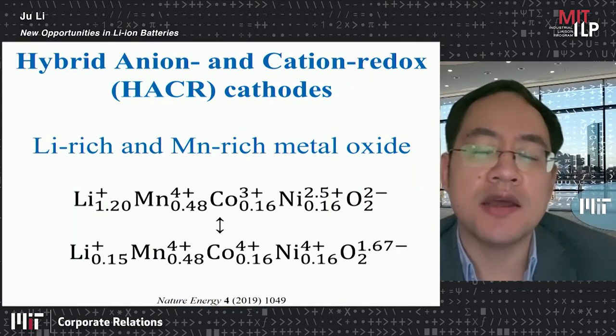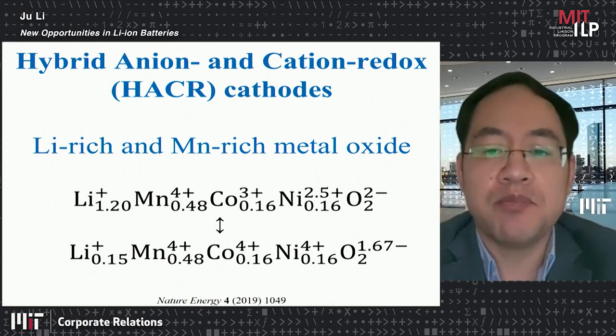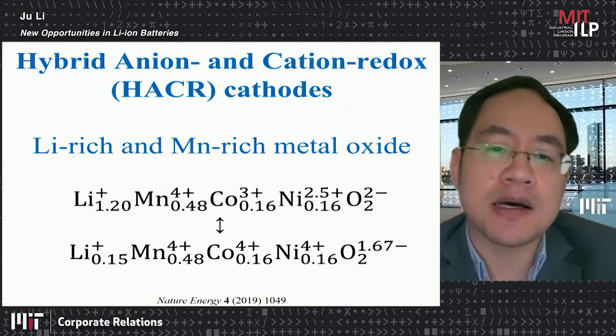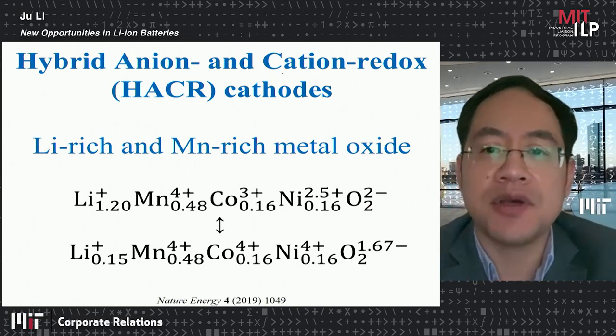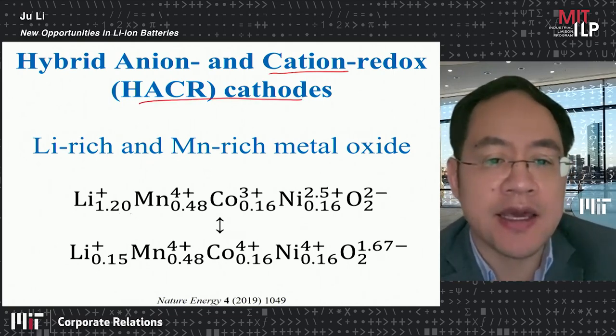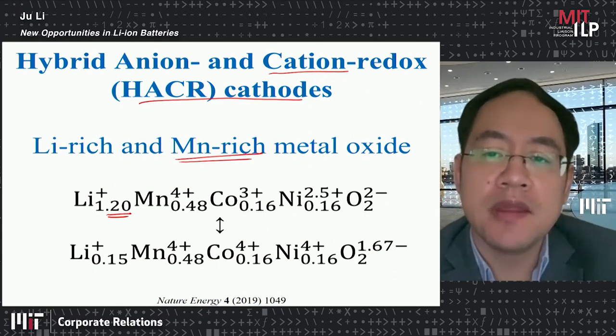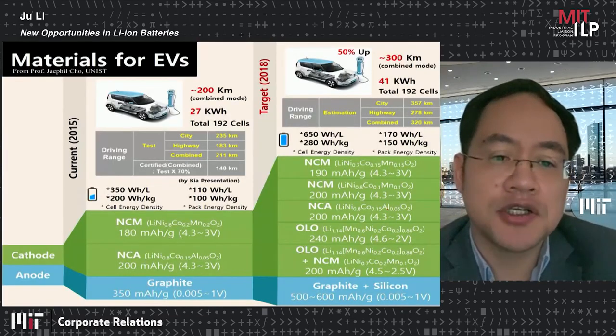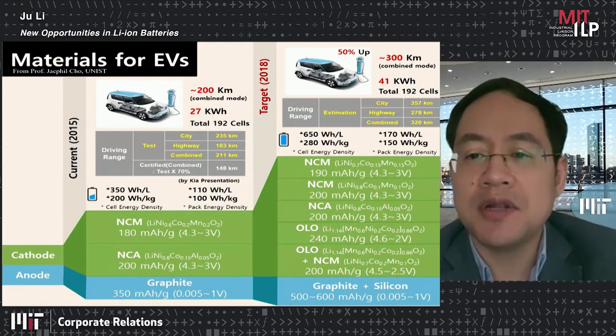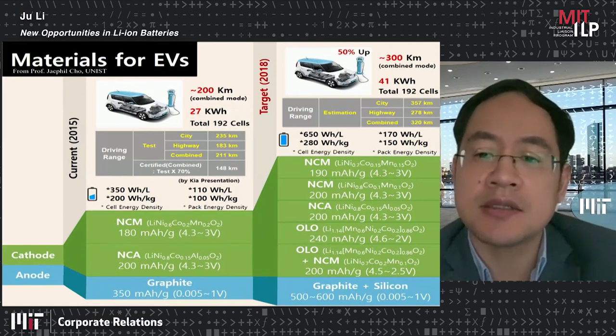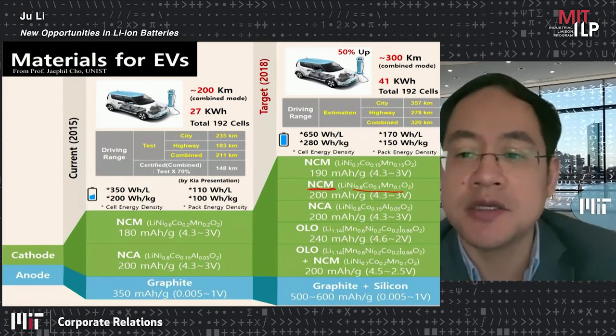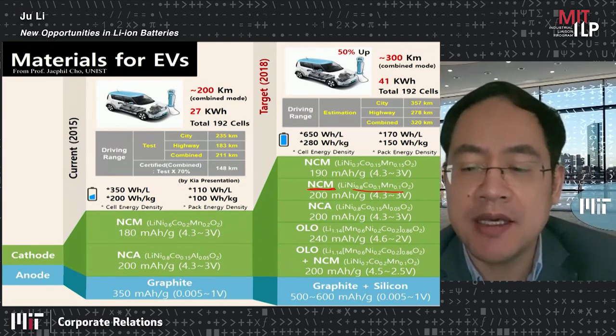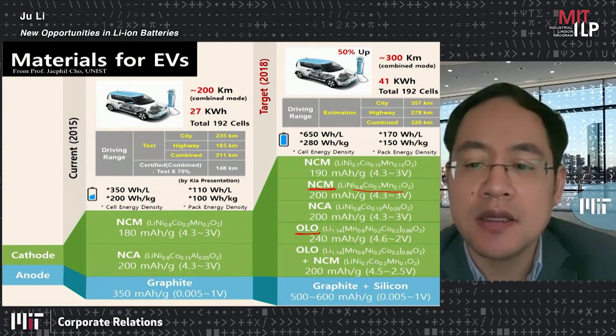Okay, so we are also thinking to do this with oxygen. And the best known system for oxygen anion redox and cation redox is this over-lithiated, manganese-rich metal oxide. So on the technology roadmap, currently we're doing 622, so that's industrialized. NCM, so nickel cobalt manganese, 811 is close to industrialization. But the next step in the process would be using this over-lithiated oxide. So 14% lithium, that's replacing the manganese, replacing the transition metal in the transition metal layer.